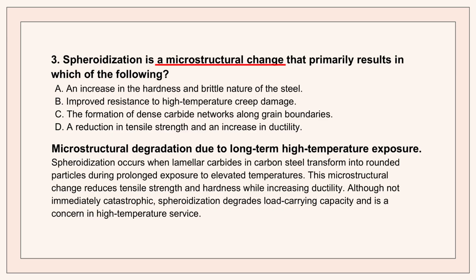Exactly. Think of the lamellar structure like strong sheets reinforcing the metal. Spheroidization is like dissolving those sheets and letting them clump into little softballs. So what's the result? The immediate result is a reduction in tensile strength and an increase in ductility. Now, increased ductility might sound good, but in this context, it's a bad sign. It means the steel is getting weaker, softer. It's degrading its core capability. It's basically aging out of service, even if the surface looks perfectly fine.